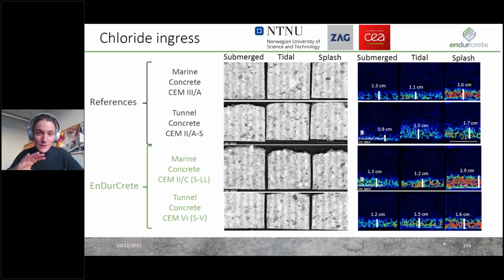As Irina also said, these are results after 1 year, and we're very interested to follow this up together with Infraplan and ZAG, this exposure site, and see how this chloride ingress develops over time. We will compare that to laboratory experiments we've done in parallel on these concretes as well. And we want to compare that with the model CEA has developed for chloride ingress, because they have developed a very advanced multi-ion model, which could account for these different exposures, because it also accounts, for example, for leaching. It's a very promising model, which we've already verified in the lab, but it would be really great to verify it with this field exposure in the long term as well. So we're looking forward to this collaboration beyond EnDurCrete. So stay tuned.